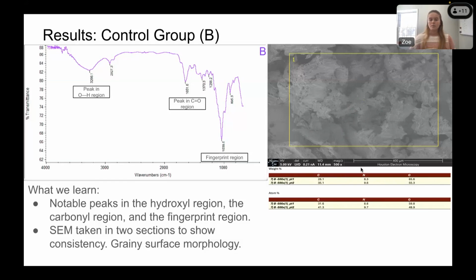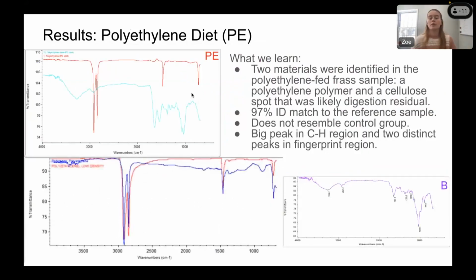So looking forward, for polyethylene, there were two materials identified in the sample. There was a cellulose part, where this is likely digestion residual, and a polyethylene spot which had a 97% match to the reference sample, meaning that in this spot, the polyethylene was not digested fully. So we're looking at a partial digestion here, and there's no resemblance of the polyethylene spot to the bran spot. There's a big peak in the carbon-hydrogen bond region and two big peaks in the fingerprint region, but it does not resemble the control group.